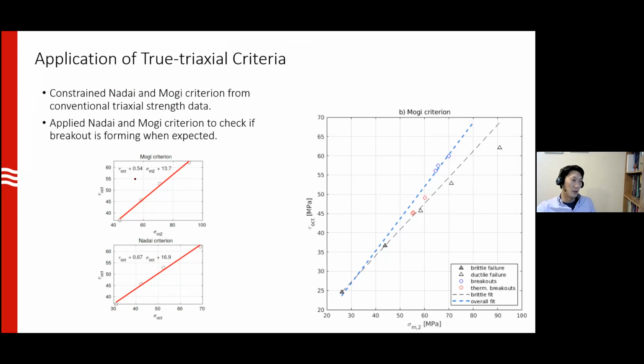So we thought we were very confident about how these criteria will allow us to predict failure. But what we still notice is that there is a discrepancy. When we compare the octahedral stress values, for instance, in a Mogi criterion, for breakout tests, that's done in a true triax setting, versus regular experiments, conventional triaxial tests, we see that these data populate in a different group.